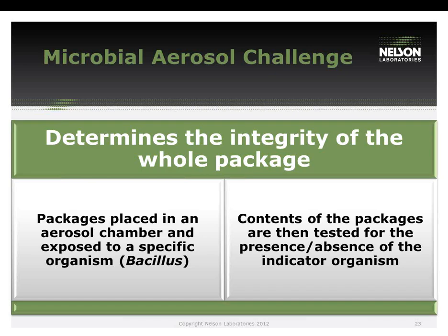And we're going to expose it again to the same organisms, except this time we're going to do it for a longer period. The F1608 test was only for 15 minutes. This one's going to go for 60 minutes, and that's going to give you a higher concentration of organisms in the chamber. So we expose it to 60 minutes of Bacillus atrophaeus, and then we evacuate the chamber, followed by letting the sample sit for a day.